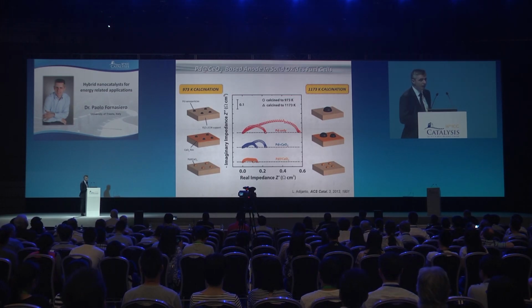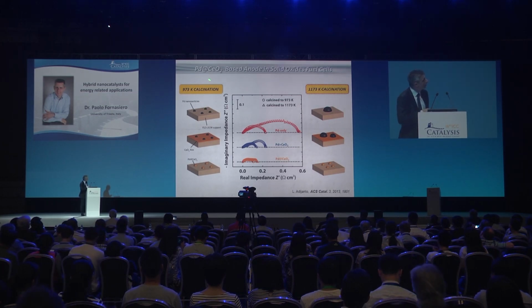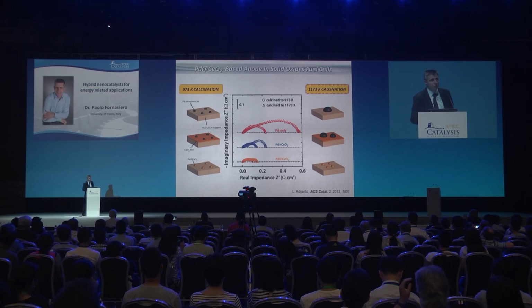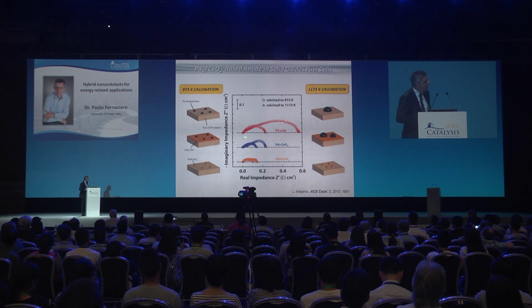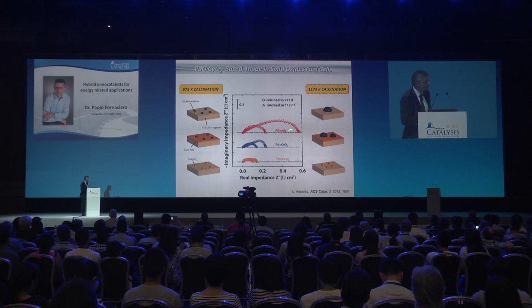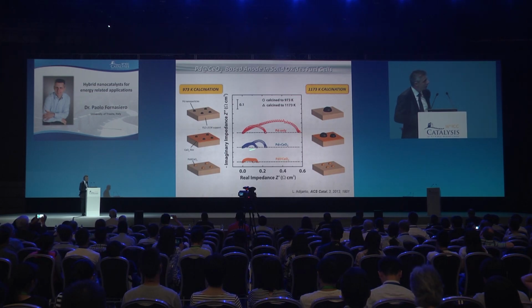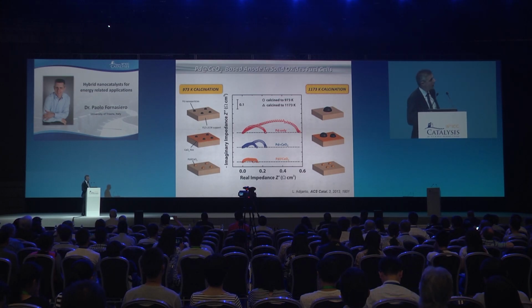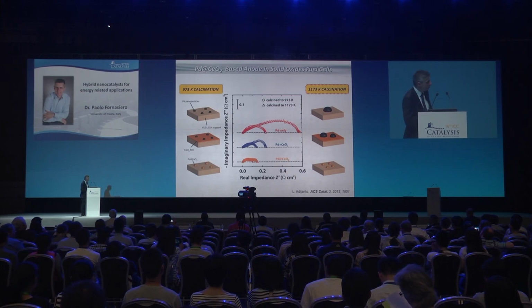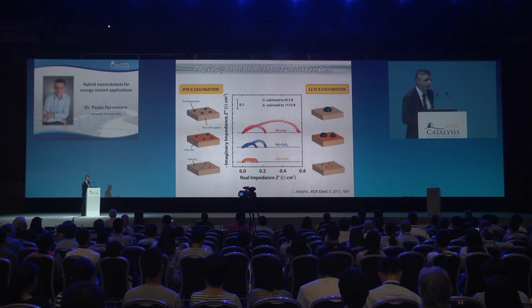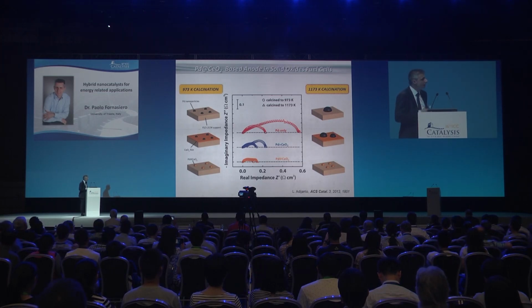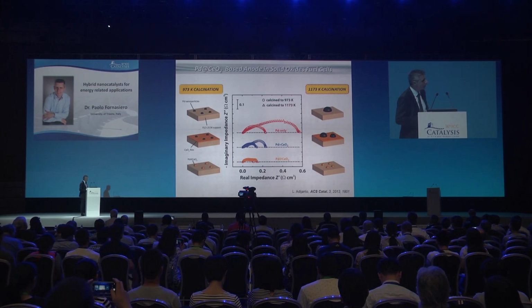The remaining part of the solid oxide fuel cell is exactly the same in all cases. And we observed the performances on fresh material and after high temperature calcination, simulating long aging of the solid oxide fuel cell. And you can appreciate here, for instance, that palladium-only technology leads to a significant deactivation. The impedance arcs change dramatically, and this is consistent with what we observe as an increase in the palladium dimension. In the case of palladium ceria prepared in a conventional manner, this deactivation is much reduced thanks to the strong metal support interaction in ceria, but still present, as observed also in the increase in particle size by microscopy. For our palladium at ceria catalyst, the system seems to be significantly more stable, really opening application in this type of catalysis.